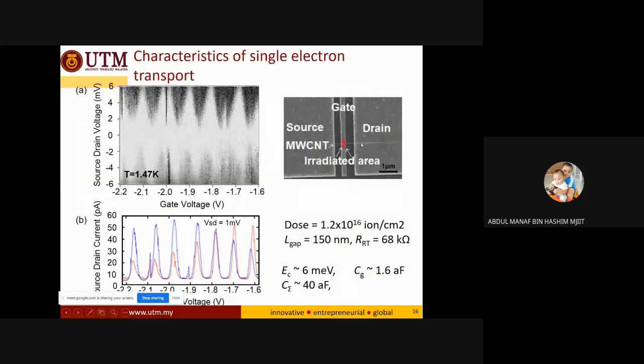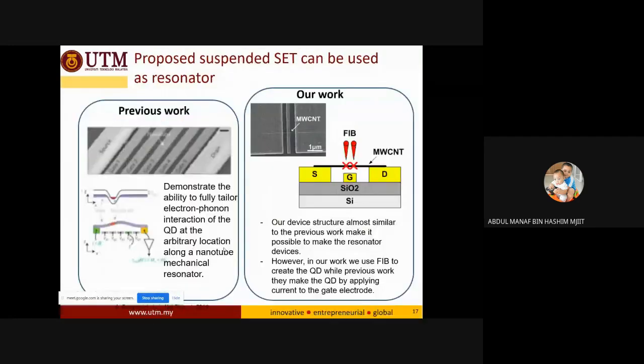By this SET structure, we measured the typical Coulomb diamond characteristic. Here we can observe the Coulomb diamond characteristic, and also the Coulomb oscillation characteristic. This measurement was done at a low temperature of 1.47 Kelvin. Our idea now, after we get this SET structure, is that we are currently proceeding to the application of this SET. We believe that this kind of device can be used as a mechanical resonator. So now it's under testing.